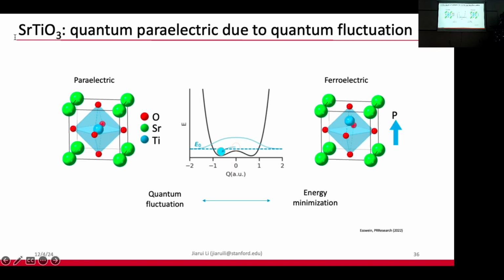So strontium titanate here also has a perovskite structure, where the titanium right now is the major player, sitting at the center of the titanium-oxygen octahedra. And it has the tendency to develop ferroelectricity, where these titanium atoms tend to move away from this high symmetry point to seek an energy minimum in this double potential well.